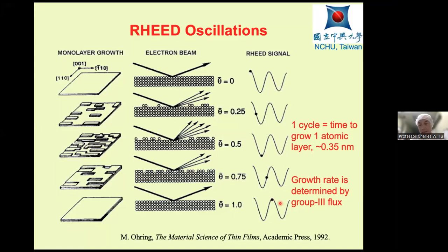In the growth of gallium arsenide, the gallium sticking coefficient is 1, meaning that once a gallium atom is on the surface, it sticks to the surface. Arsenic has a higher vapor pressure. The arsenic sticking coefficient is 1 if there is a free gallium, but if there is no free gallium, then the sticking coefficient is like 10 to the minus 5 or something like that. So our growth of gallium arsenide is controlled by the group 3 flux.